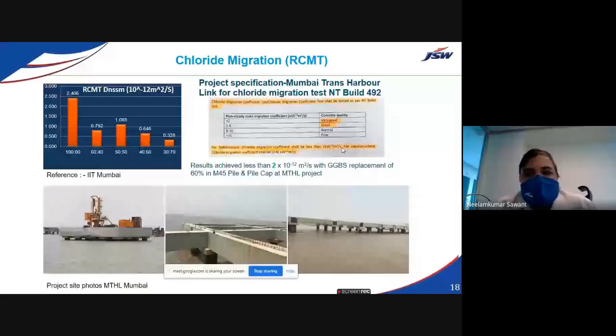You can see the migration coefficient is less than 2. Whenever it is less than 2, the concrete quality is very good, and if it is 2 to 8, then it is good. Whatever the migration values are, they are all mentioned in this table, and we are getting results which are less than 2 in case of GGBS replacement, about 60% in M45 grade of pile casting as well as pile caps for these projects. So these are the proven tracks.